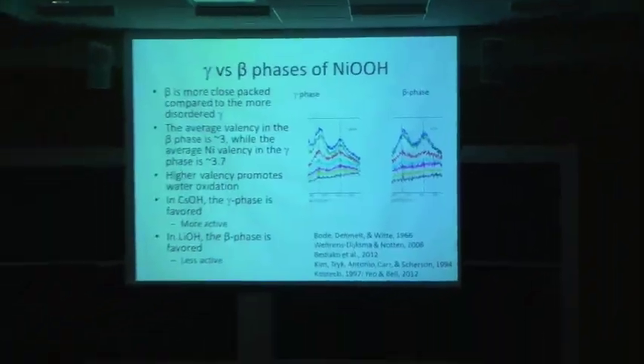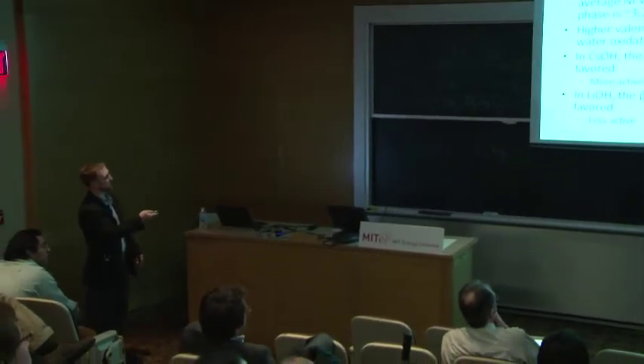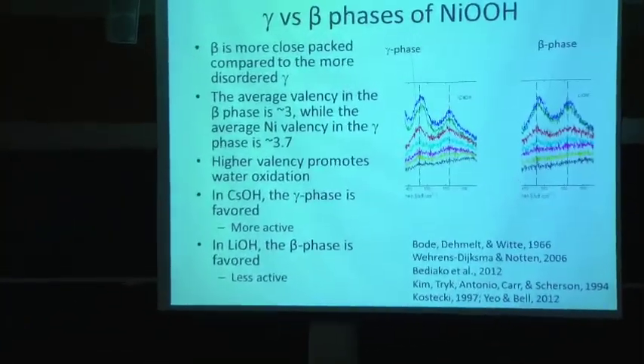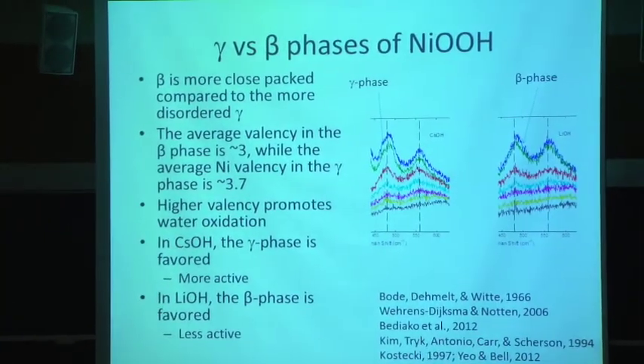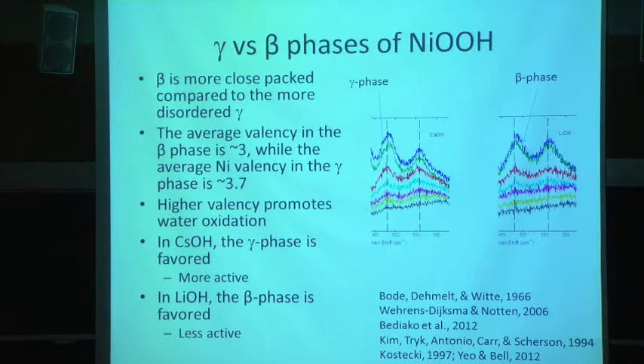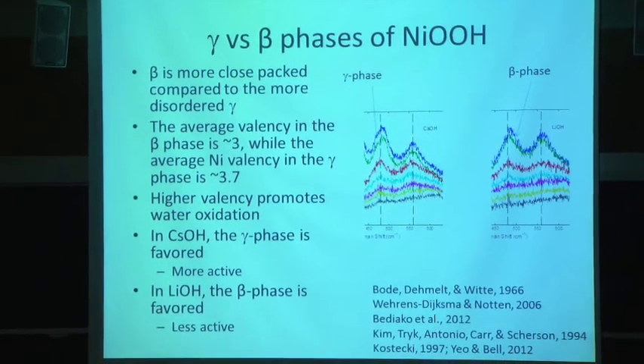So now, how do we make sense of all of this information? I'm going to focus now just on the most active and the least active. So here's the most active, cesium hydroxide, least active, lithium hydroxide. It's clear that these phases are forming at a much lower potential in cesium hydroxide than they are in lithium hydroxide. So if the oxyhydroxide phase is the active phase, then it's no surprise cesium hydroxide is more active because you form the active phase at a much lower potential.